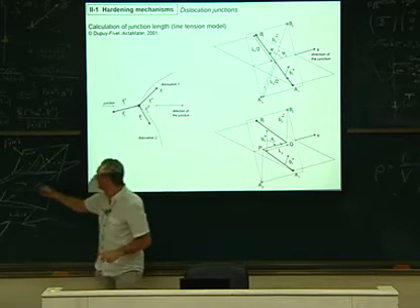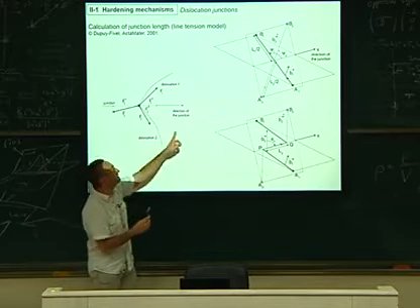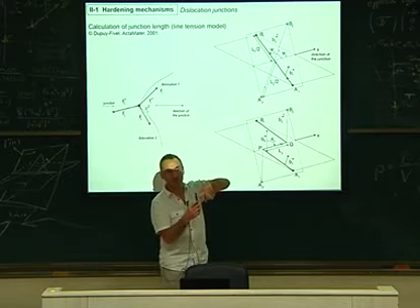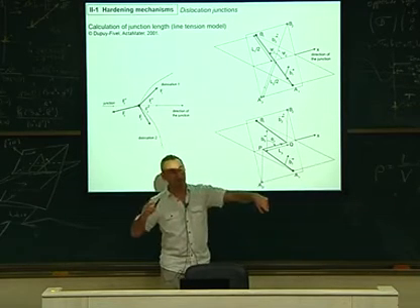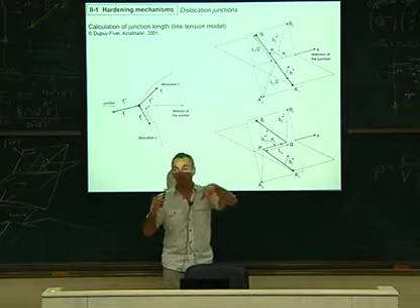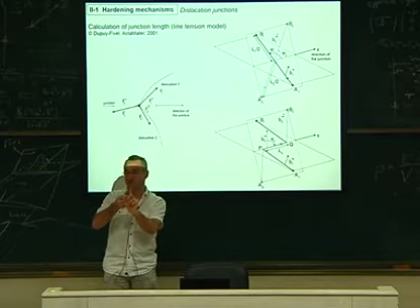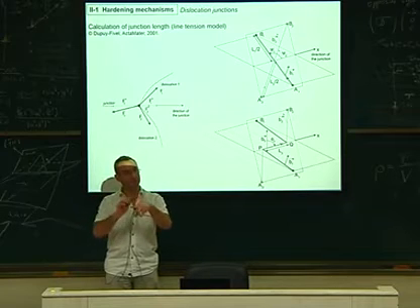Because in some cases, if we reverse the sign as we did here, if we take the opposite sign, so that phi is bigger than 90 degrees, for example, then they will repel. They will not form a junction, so they will be repelling dislocations. So for the same dislocation interactions, same Burgers vectors, some are attractive and some could be repulsive. It just depends on the line orientation. Okay?